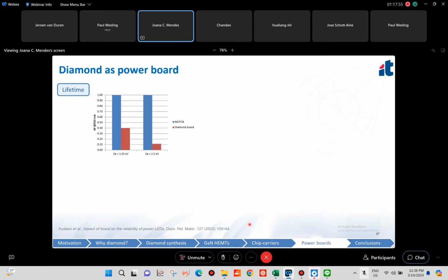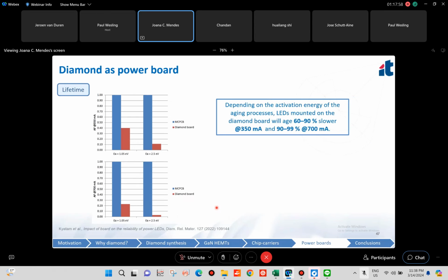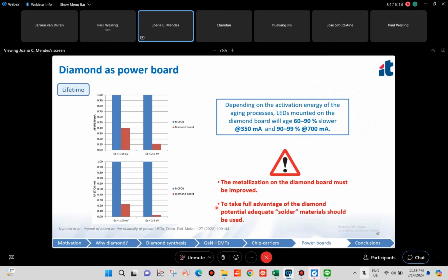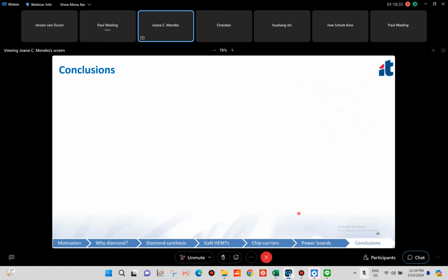And then we also evaluated the impact of the temperature on the lifetime, and depending on the aging process, again on the activation energy, the LEDs mounted on the diamond board will age 60 to 90% slower at 350 milliamps and 90 to 99% slower at 700 milliamps. However, to really take advantage of diamond, first we need to improve the metallization of the diamond boards, and we have to use adequate solder materials or thermal interface materials, whatever you want to call them, with high thermal conductivity. The conclusions of my talk.